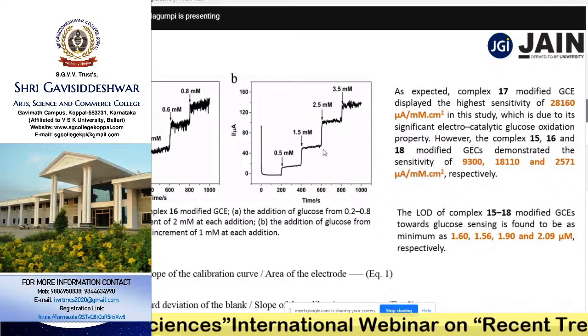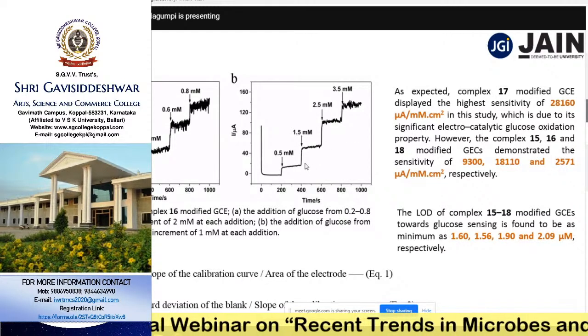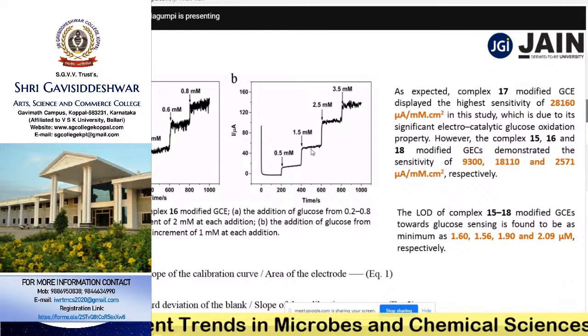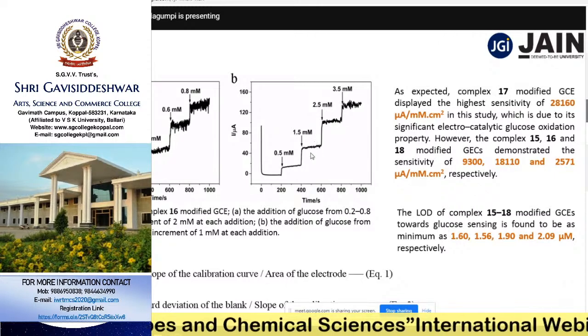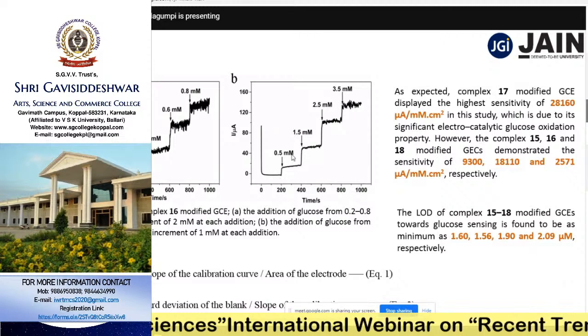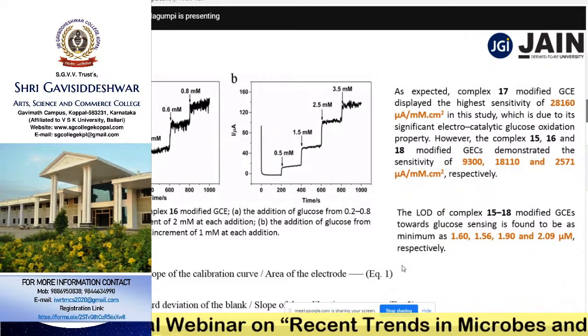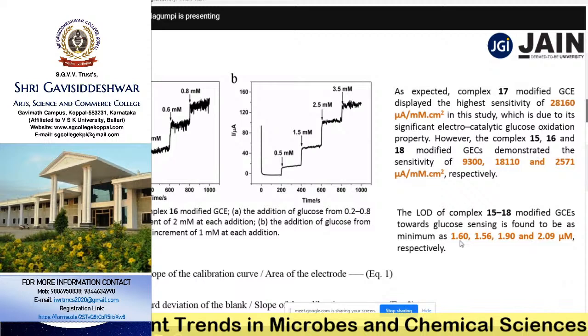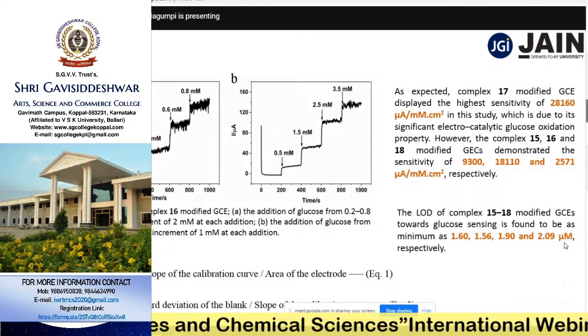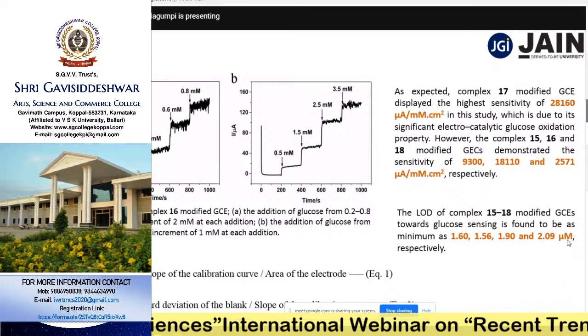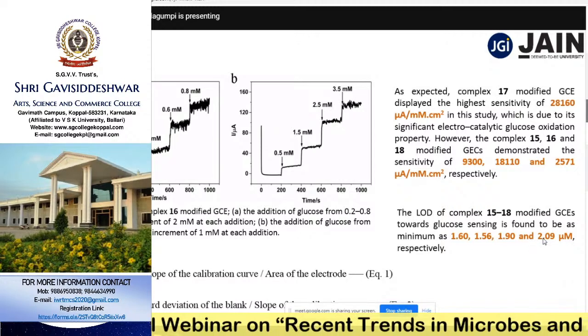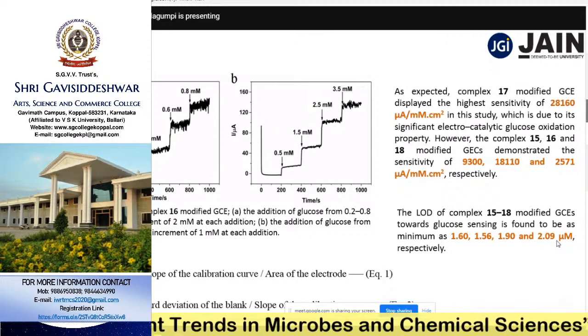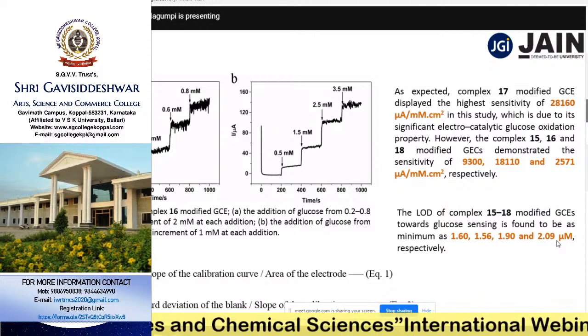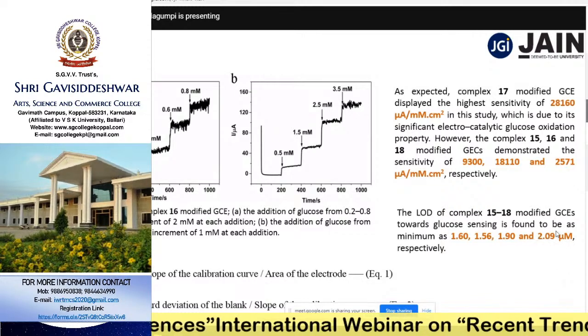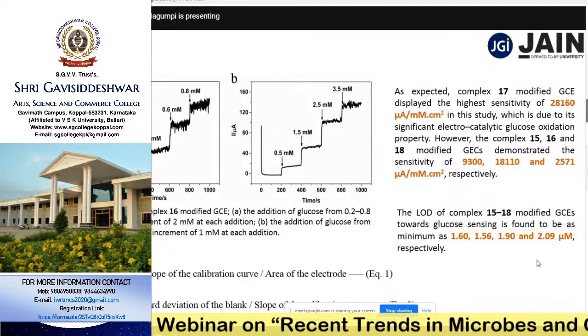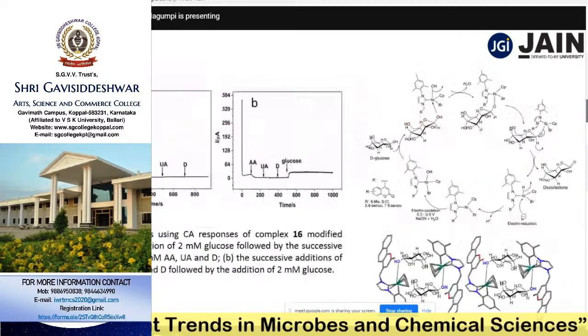This is like how we find the unknown concentration of a copper solution using the Beer-Lambert law, right? In a similar way, one can easily identify the amount of glucose present in blood samples, and the limit of detection of these complexes is somewhere around 1 point something, or maximum 2 micromoles. You can identify even 2 micromoles of glucose in blood samples. Blood glucose level is up to 6 to 8 millimoles, while we could identify even this smaller amount of glucose, which means they are highly stable and highly sensitive.